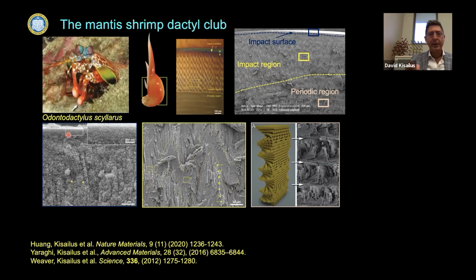And I like to make analogies. If I'm an angry teenager and I like to punch a wall because I'm angry, I may break my knuckle because of a local contact stress on my knuckle. So imagine the mantis shrimp smashing thousands of times, but it doesn't develop these high localized stresses. Why is that? And so we believe these coatings of particles coat the club and actually reduce those localized contact